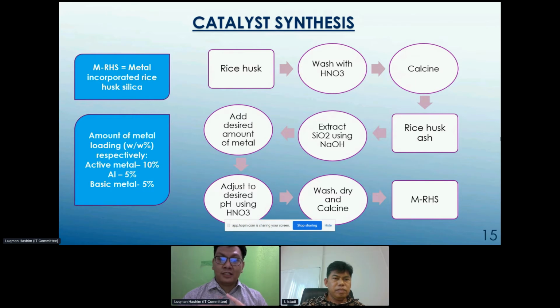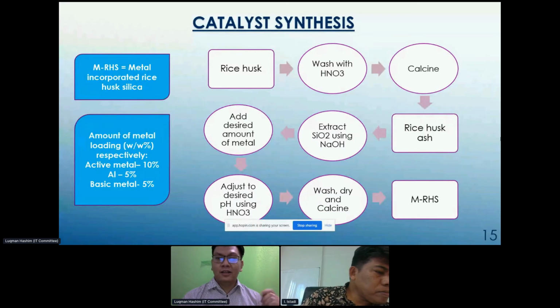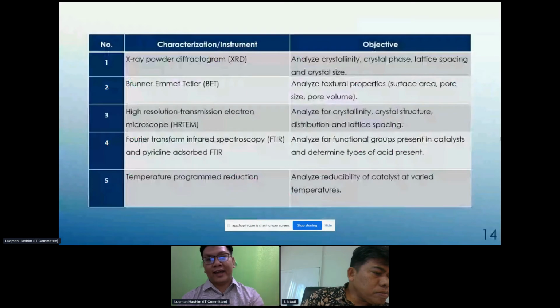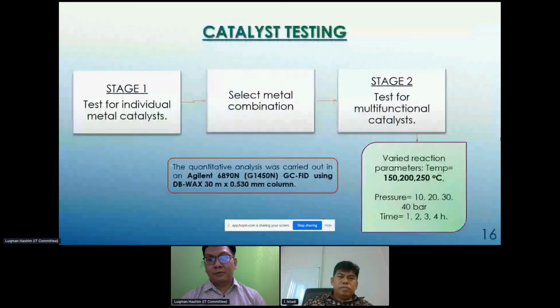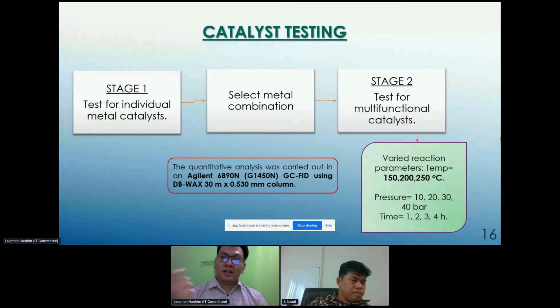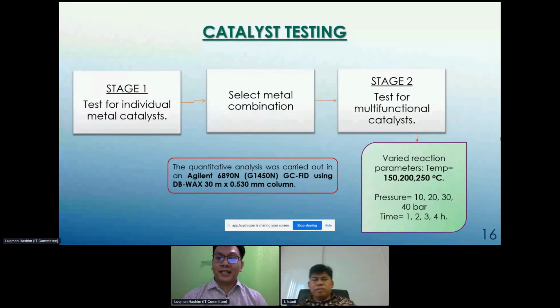And then we adjust the pH of the mixture using nitric acid, added gradually to the desired pH, which in this case is pH 3. I forgot to mention that, sorry. After that, we wash, dry, and calcine to finally obtain our desired catalyst as stated there at the catalyst batches. So now, very briefly about our testing process. We are going to use a batch reactor with ethanol as the solvent for the reaction. We will add the catalyst, the furfural, and also the acetic acid, so that we are going to do, as I said before, a tandem hydrogenation esterification process in one pot. That means after hydrogenation takes place, esterification will take place on the same catalyst. So I just want to draw your attention to the varied reaction parameters, the temperature, the pressure, and the time there.